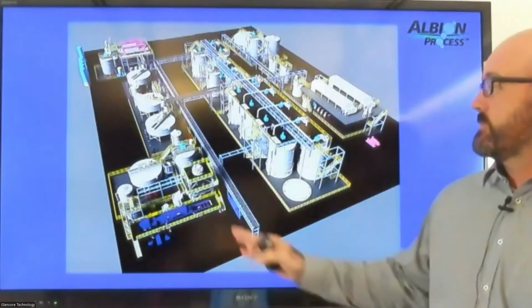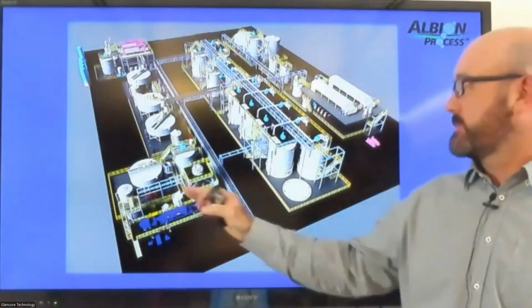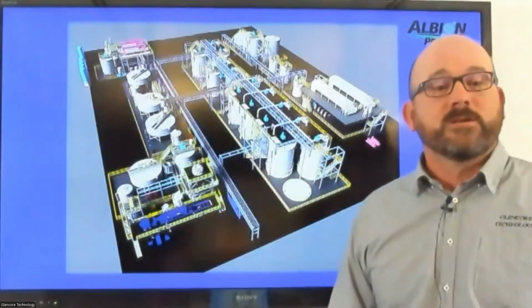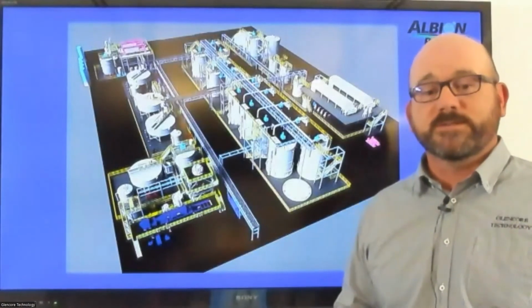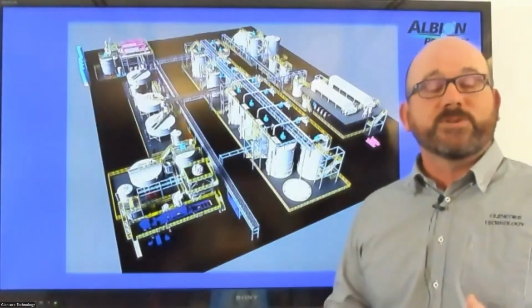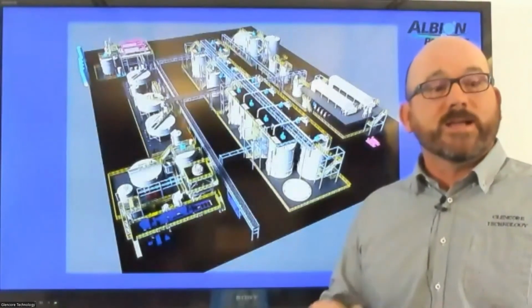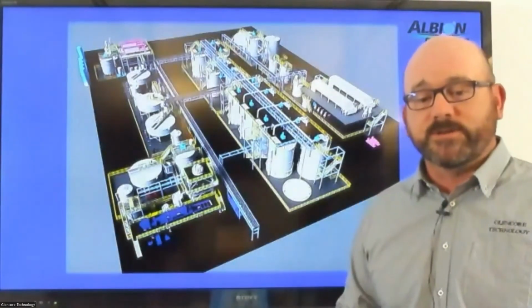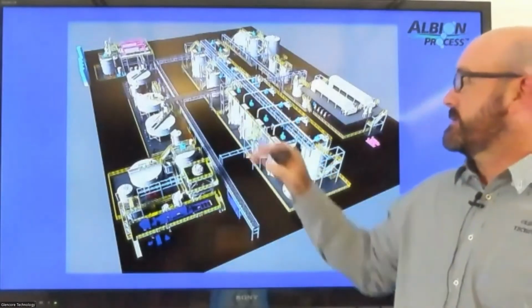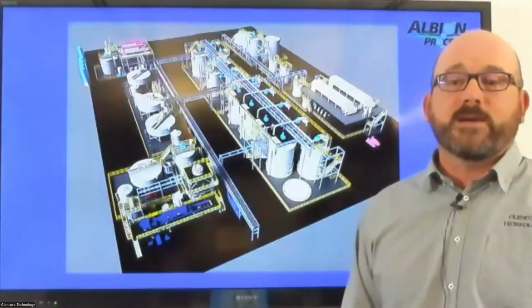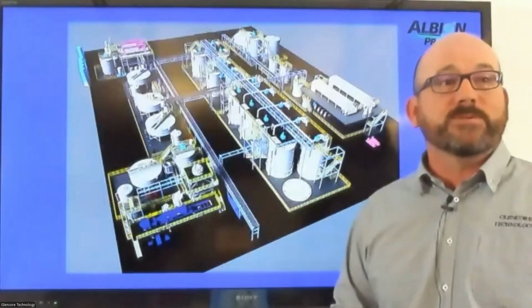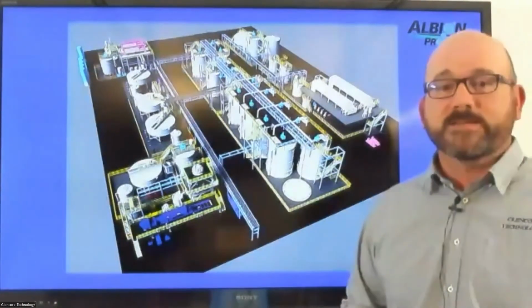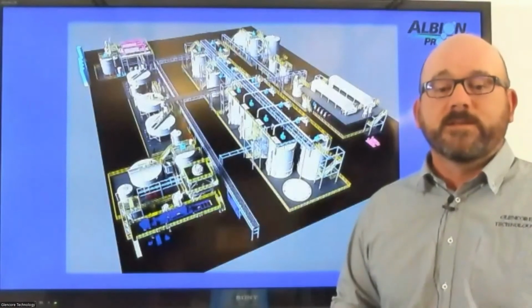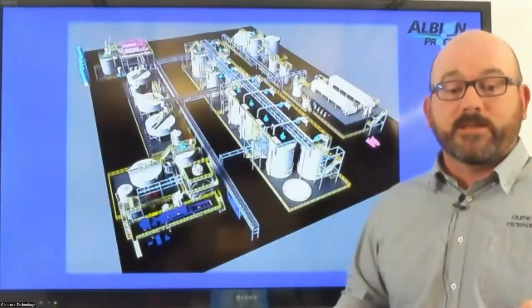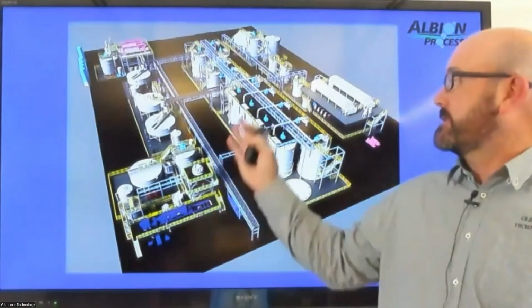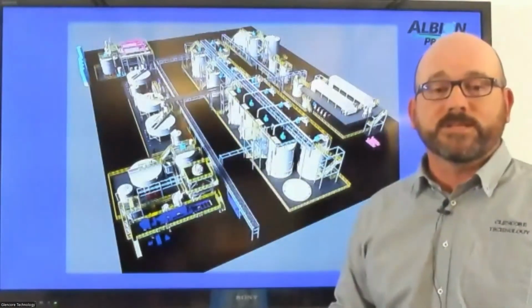From the IsaMill, we go into a concentrate feed tank, which feeds into the first 3 of the Albion process tanks. This allows you to bypass the first tank if there's an issue, and still maintain the operating circuit. For this, we have 6 tanks running under acid Albion conditions to liberate the base metals. That's running at a free acid of about 10 or 15 grams per litre. And then straight from there, it's going into 3 iron neutralisation tanks.